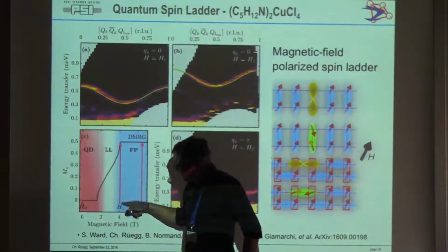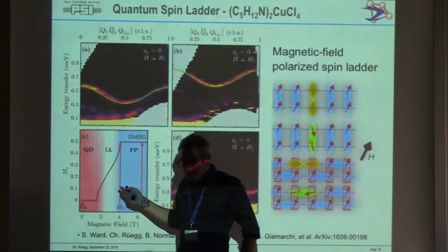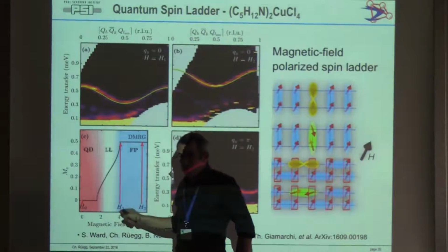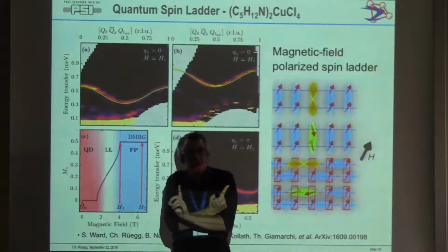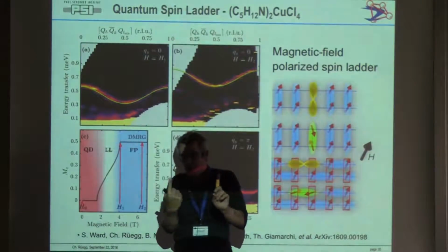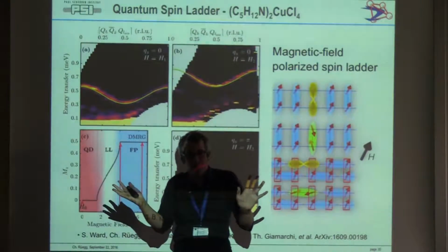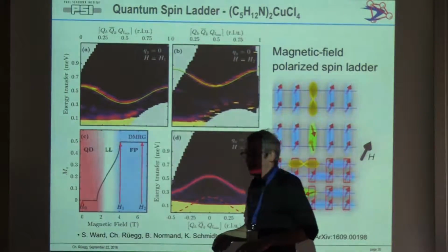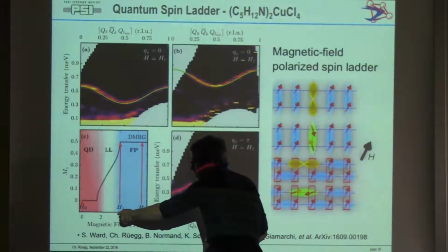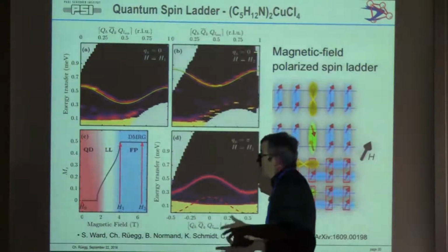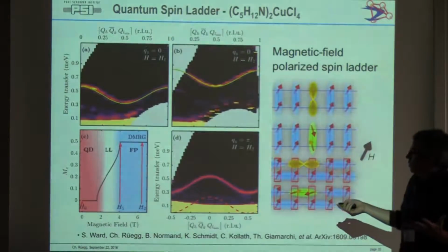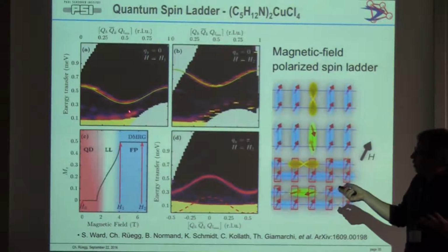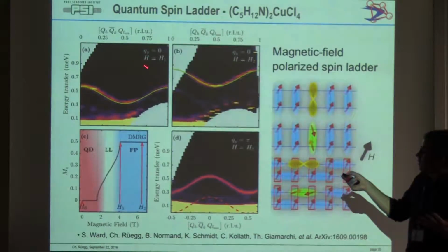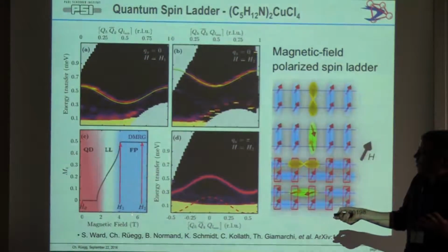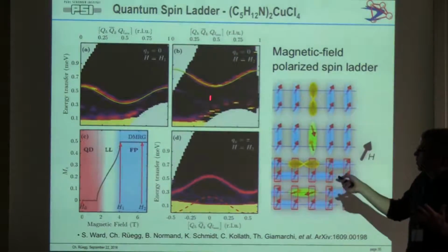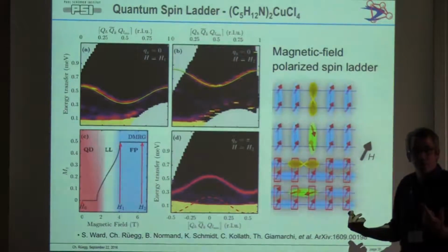If you go then to higher values, and I said that these systems could be like switches, you essentially go to fully saturated. If you apply a very strong field, all spins are field aligned. So you have a ferromagnet, no fluctuations. That's your classical magnet you want. And the gap would increase from here, 0, to a finite value linear with the field. This you can also do in experiments. So then you would expect simply cosine type ferromagnetic spin waves with a quadratic dispersion here. And that's exactly what is measured. So we apply, in this case, fields in excess of 4 Tesla. And then you see these branches, which exactly are the ferromagnetic spin waves.